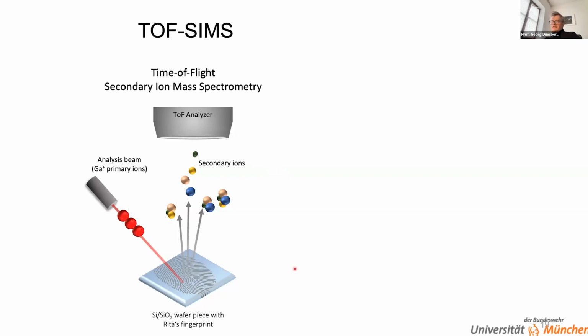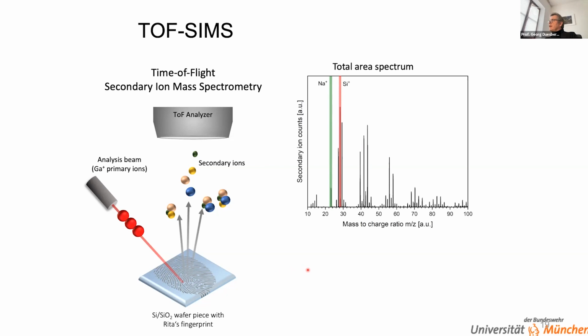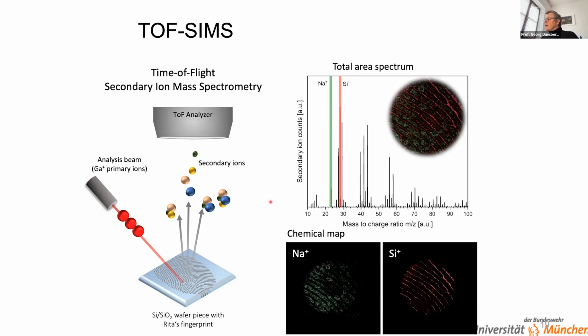And this is shown here for a fingerprint of my student Rita. She looked at her fingerprint on a silicon wafer, and she can look at the sodium and the silicon peaks here. And if you map the sodium and the silicon, you can see that the sodium just from touching the finger shows up perfectly in comparison to the silicon in between. So for all those who work in the clean rooms, that's why you should be wearing gloves when you handle your samples.